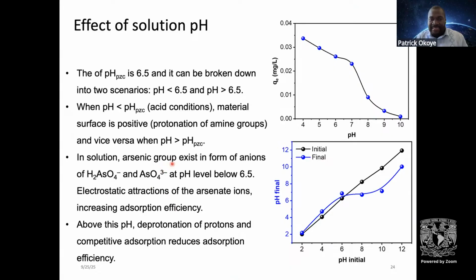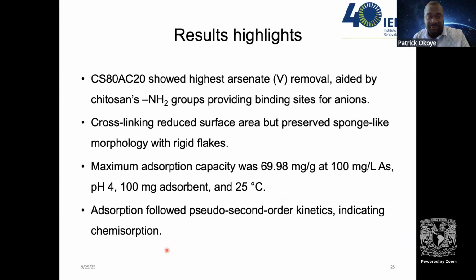So in solution, arsenic exists in the form of anions, which are negative, at pH below 6.5. So it is easier to take up because our surface is positive. But if we go to a pH above that, there is deprotonation, and the ions have competitive adsorption, which reduces the adsorption efficiency. And our results showed that this material was more efficient due to the amine groups on the surface. And the cross-linking reduced the surface area,